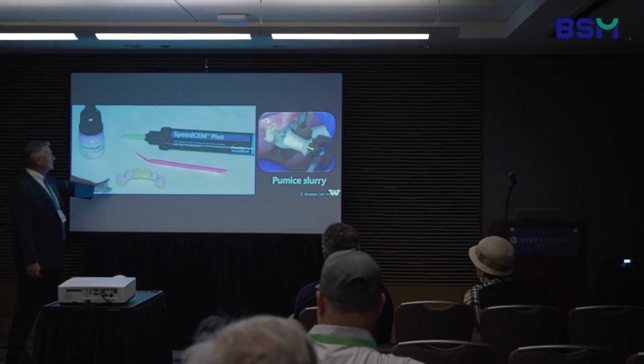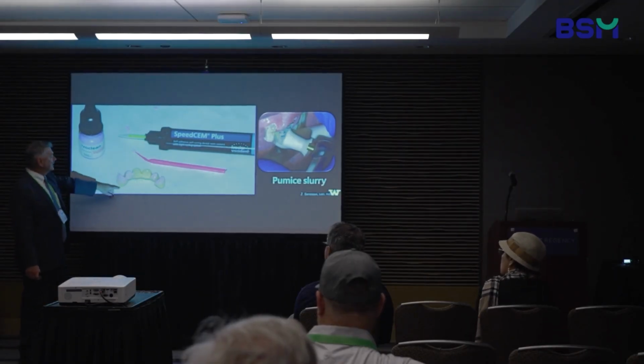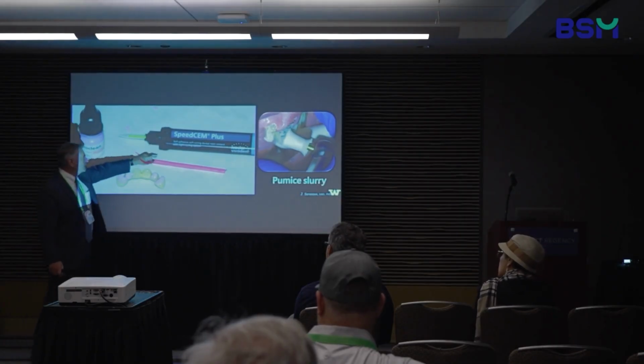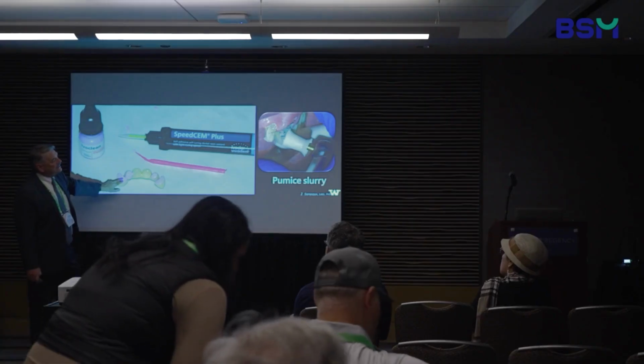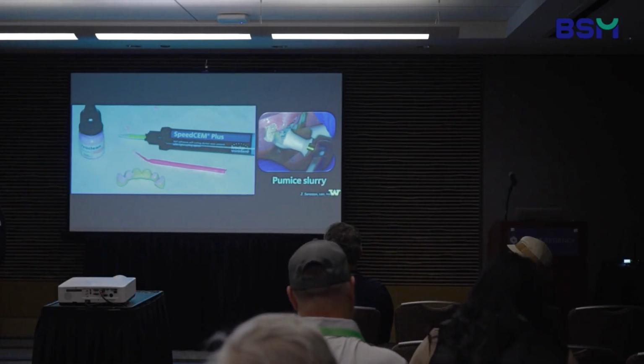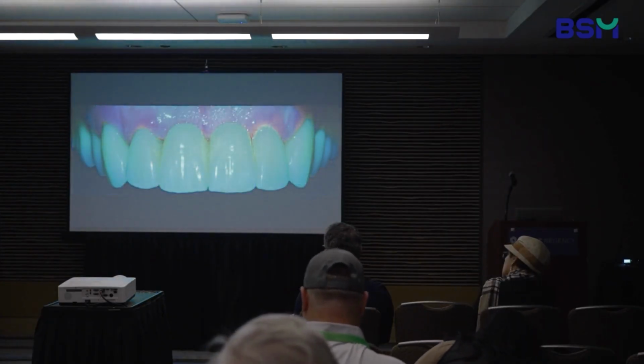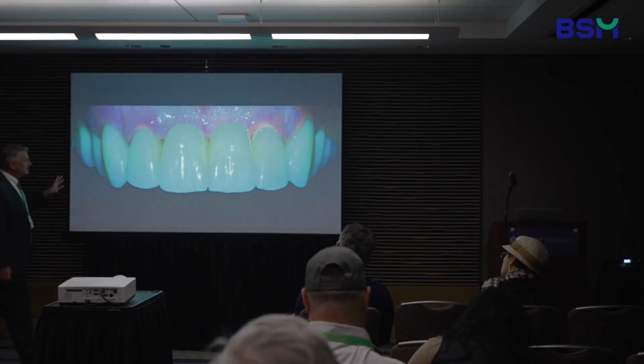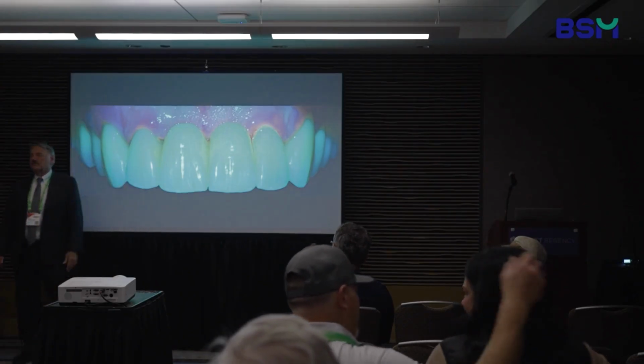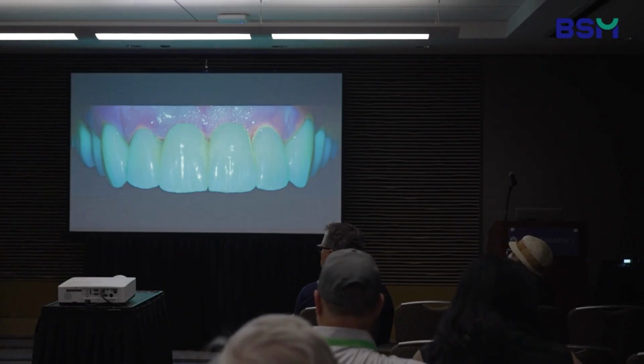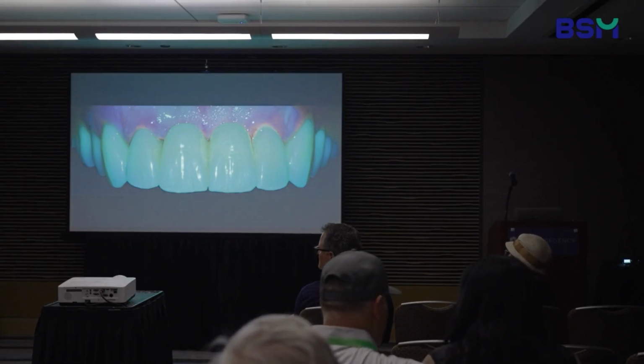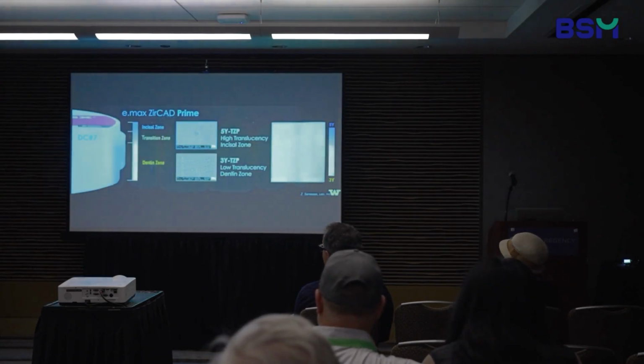So again, in this case, we're delivering the bridge. We're going to go ahead and use the SpeedCEM material and again clean that surface, and then we're going to pumice, slurry, clean the tooth preparations, rinse it off and dry it, and cement the restoration, and it just looks like tooth structure. And all we did was mill that out of the disc for that. So really nice that we can get those kind of results. I ended up doing this all digitally with a patient that was flying in from out of town.